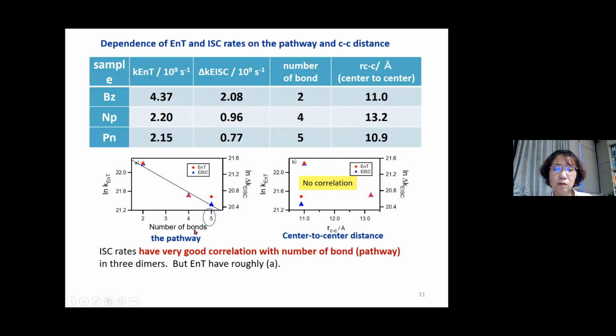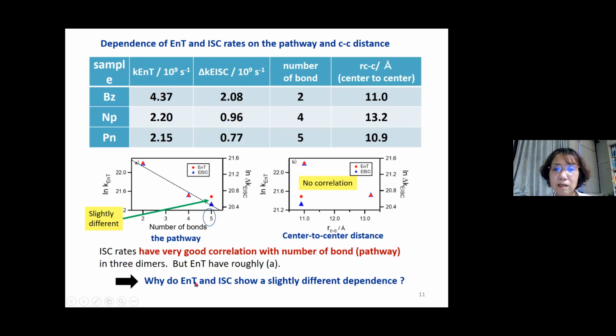So we thought that the enhancement of energy transfer and intersystem crossing is governed by some three bond superexchange-like interaction, but we have to notice that there is a small difference between the enhanced intersystem crossing and energy transfer rates. So why do intersystem crossing and energy transfer rate show a slightly different dependence? This gives us a hint to consider the mechanism.